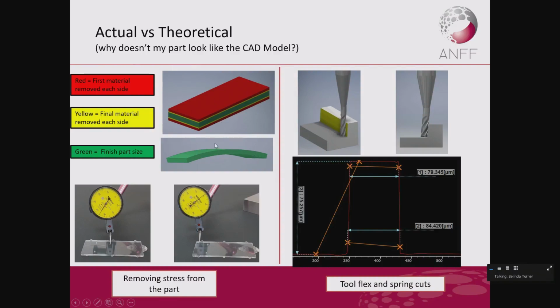The first one is the material. When it's made, there's often stress put into this material. So if we take a small layer off each side of this polymer, for instance, it'll start to distort and de-stress. So we might have to take the 2 red layers off the top and the bottom, and then take the other layers off just so we can de-stress it and hold it in a way where we're not putting stress onto it. Because even holding under vacuum, you're still putting stress on this part and it's still moving, and when you release it, it's going to flex back in a different orientation. And this doesn't usually matter for general machining in industry, but when you're making really small features or small parts, it makes a big difference.